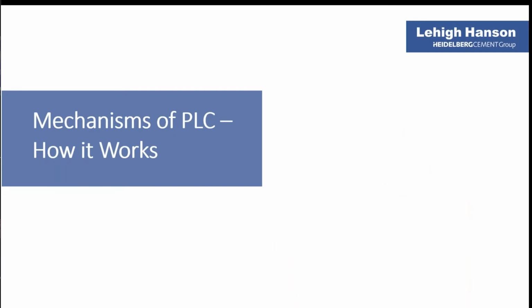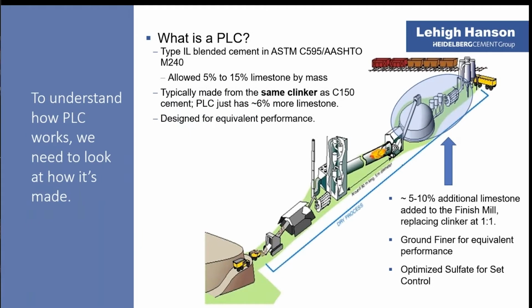So as we talk about how it works, let's get into the mechanisms of PLC a bit. And really to understand how PLC works, we need to look at how it's made. As I briefly mentioned, type IL is a blended cement, and it's covered under ASTM C595 and AASHTO M240. Under those specifications, it's allowed 5 to 15% limestone by mass. And this next point is something that I want to make sure everyone understands, because this is the question that I routinely get. Portland Limestone Cement, our C595 cement, is very typically made from the very same clinker as the C150 cement from that same cement plant. The only difference is that PLC just has roughly 6% more limestone. And a key is because it is a blended produced cement, it is designed for equivalent performance. And we're going to talk about that a bit.